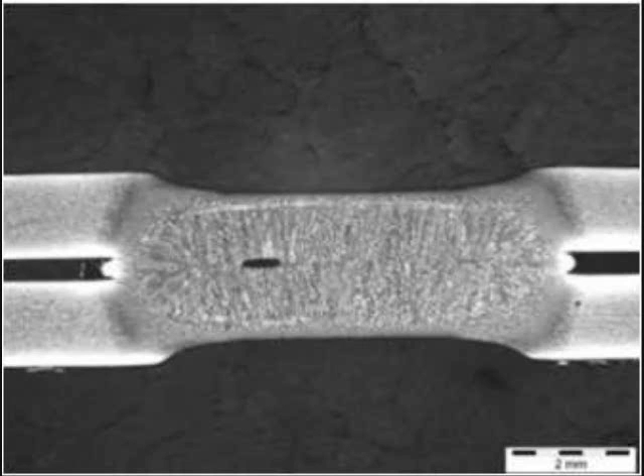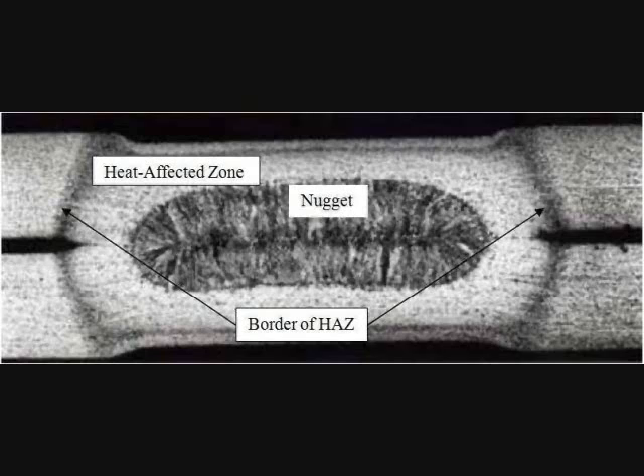This picture is an expulsion weld. You can tell from the cavity in the middle, the deep indentation, and the sheet separation. This is the picture of a high temperature weld. You can still see very deep indentation, and although there is no cavity there, you can clearly see the HAZ and the border of the HAZ.